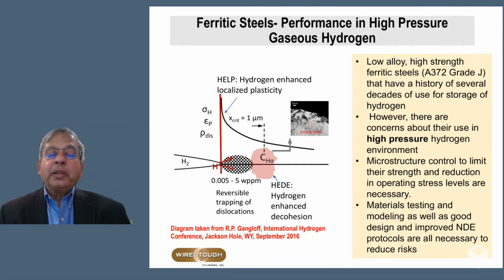It has been known for a long time that if you have a defect, for example, in ferritic steels that is being exposed to gaseous hydrogen, you have several mechanisms of damage that cause the cracks to grow faster, or essentially have environment-assisted cracking, which is faster than what you see in non-hydrogen or innocuous environments. Some of those mechanisms are hydrogen-enhanced local plasticity, reversible trapping of dislocations, and hydrogen-enhanced decohesion. These all occur, and we have to test the material to make sure that we have properties that have been obtained under these high-pressure hydrogen conditions, and the measured crack growth rates account for some of these